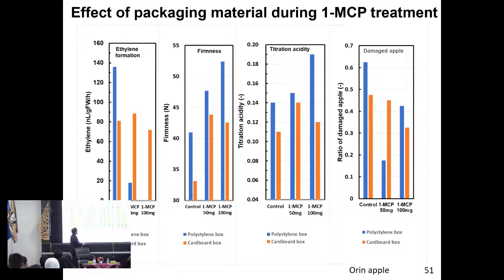And then we have to see this damaged apple, some kind of apple that has damage. Control case, 60% of the apples are damaged after 1 month. But when we use the 50 milligram case, below 20%.